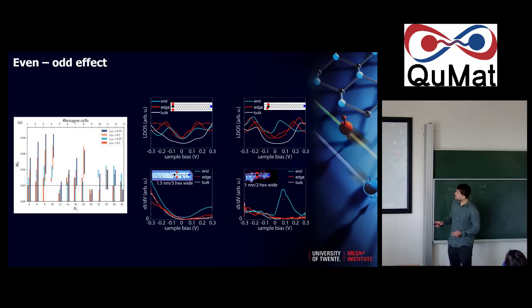This is again the even-odd effect I showed you before. You see the phase diagram for different spin-orbit coupling, and you see the staggered mass as a function of the width of the nanoribbon, or the number of hexagon cells that you have. And you see that you get some behavior that looks a bit like that. So you have a reentrant behavior. We go from topological to trivial, topological, and so on, depending on these parameters.